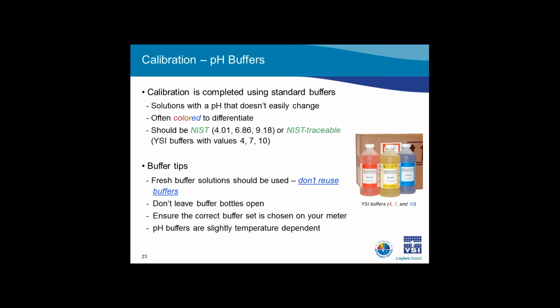Just as important as using traceable buffers is making sure your solutions are fresh and not contaminated. Old or contaminated buffers will introduce error in your calibration and subsequent measurements. So check the expiration date on your bottle and note that buffers actually have two shelf lives, one unopened and one opened. For example, YSI buffers have a 2-year shelf life unopened, but once you open it, the shelf life is reduced to 6 months. So check with the manufacturer of your buffer solution to obtain this information and write the date you open the buffer right on the bottle.